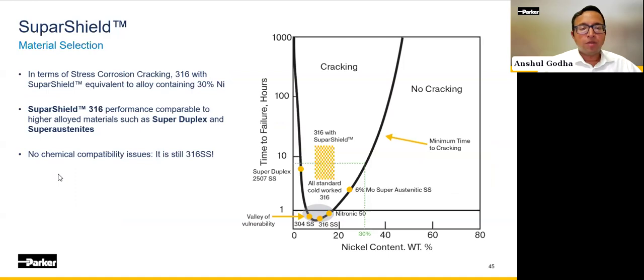Paula had earlier shared the Copson curve and how it plots the nickel content with the time to failure in a boiling magnesium chloride type setting. Here we have overlaid the different alloys along with the 316 Super Shield product as well. And what is interesting to note here is the improvement in performance is so substantial that a 316 cold worked alloy can give you a similar performance to another alloy which has up to 30% nickel in its chemistry. So it's really dramatic.